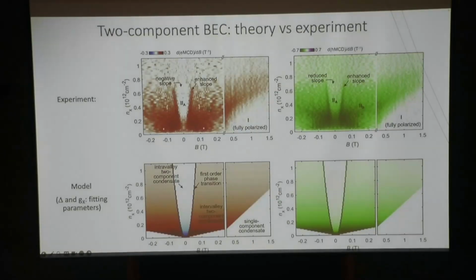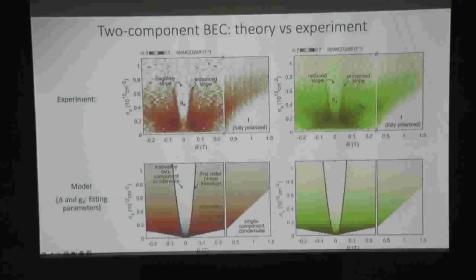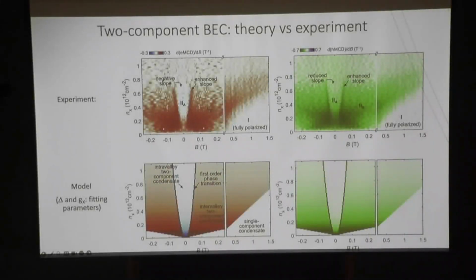With this relatively simple interacting boson model, there are only two unknown parameters that we need to use as fitting parameters. One is the single particle energy separation. One is the effective G factor. Then the theory actually can predict the rather complex experimental observation quite well. So there are three different phases. And at finite magnetic field, you can have a first order phase transition from type 2A to type 2B. And then the electron side and hole side are completely matched with each other. And also the phase region expands when you have higher density because the exchange interaction becomes stronger.